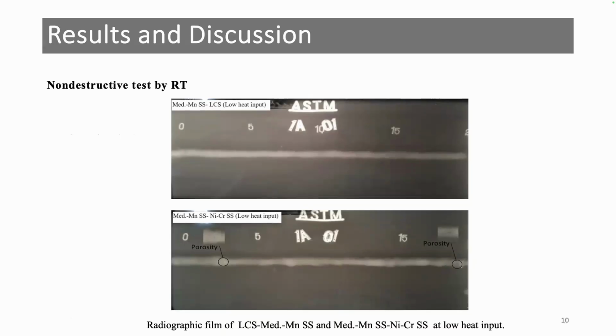Then after welding, we start with the radiographic test to ensure that the welding has good properties. We found that some porosity was formed at the edges of the welding joint, therefore it was neglected, and the specimens for tension test and hardness were selected from the center.